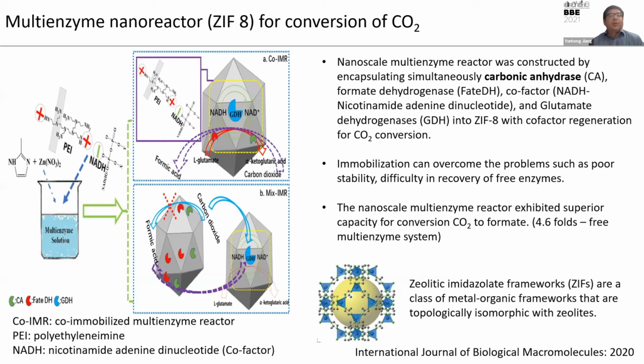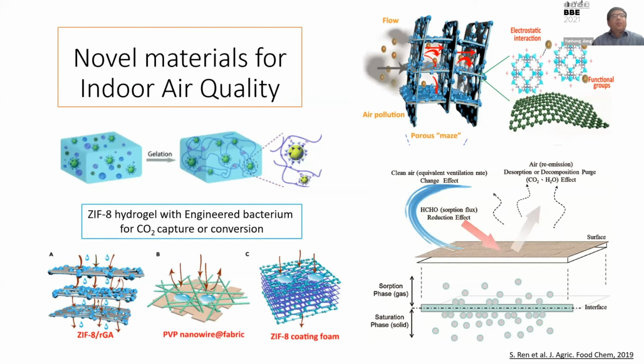In this slide, we also use the ZIF MOF material to encapsulate the carbonic anhydrase, FateDH, NADH, and GDH for enhanced formate yield rate. The system shows super capacity for conversion of carbon dioxide to formate. The detailed experiment can be found in the paper published in the International Journal of Biological Macromolecules, 2020. So, based on these two collaboration projects, I'm also interested in developing the bacterial cellulose hydrogel membrane as a nanoporous carrier for improving indoor air quality through carbon dioxide capture.